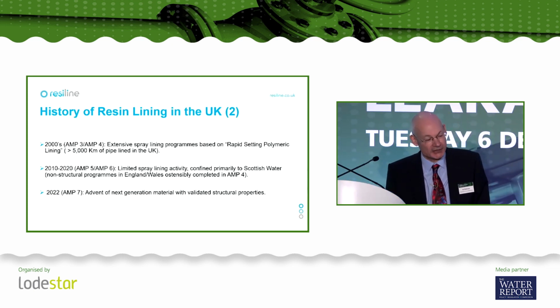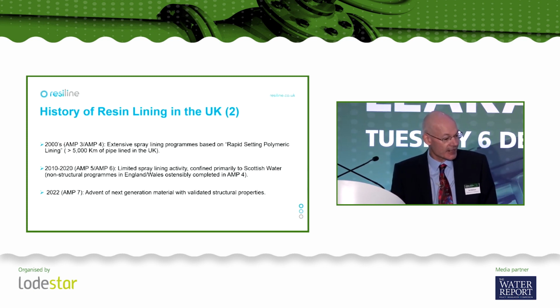Now, fortuitously, the launch of that product coincided with the commencement of AMP3 back in 2000, and the concept of rapid setting polymeric lining was wholeheartedly embraced by some water utilities, specifically Yorkshire Water and South West Water, and they did huge amounts of spray lining during AMP3 and AMP4. In fact, in the UK, over 5,000 kilometres of mains were rehabilitated using this material. Now, those programmes largely came to an end around 2007, 2008, as AMP4 wound down.